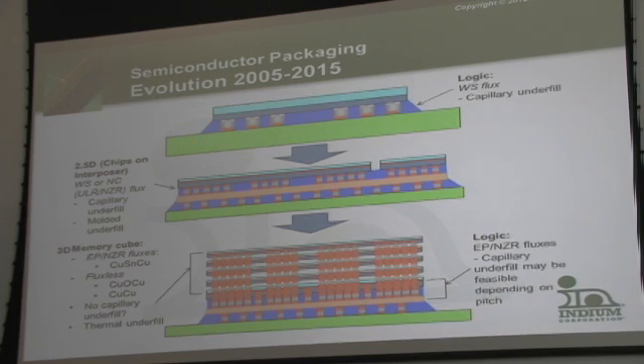The 2.5D, I mentioned earlier about the delicacy of the ultra-low K dielectric, which is here sort of slightly represented by the grey on the surface of the chip. As the material gets more and more delicate, obviously, you are exposing it to the stresses associated with attaching something which doesn't expand and contract very much with temperature to something like this green substrate, which does expand and contract to a great extent with temperature. You get a lot of shear stresses which can be caused simply by warming the substrate up and then cooling it down.